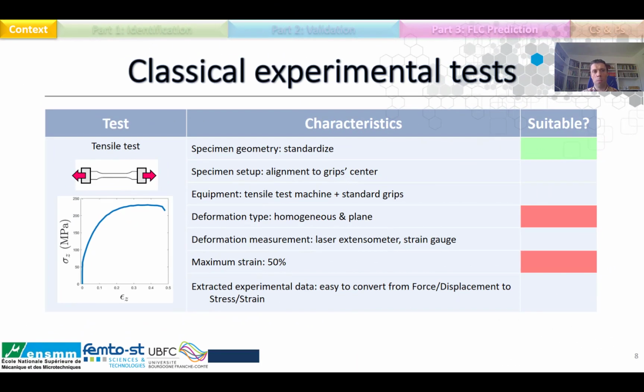So the most known experimental test is tensile test. Tensile test have two main weaknesses for the work we are trying to do. First weakness is that tensile test goes under homogeneous and plane deformation, and maximum strain for copper alloy, it's rarely above 50%. So this doesn't match the requirements we have for our characterization, which is out of plane and maximum strain above 100%.